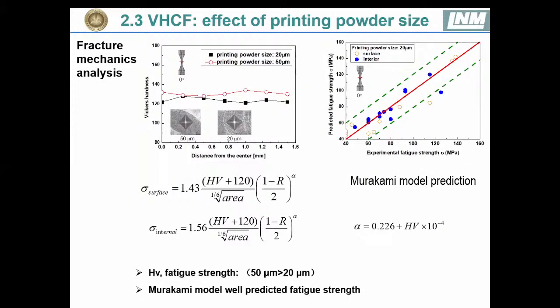And in order to study fatigue strength, the Murakami model will be used. The Murakami model is a traditional and quite widely used model to predict fatigue strength. It correlates fatigue strength with Vickers hardness, the square root area of the defects, and the stress ratio. Here, for both surface and internal crack fatigue strengths, the Murakami model predicts quite well, with the result showing good agreement with the experimental results.